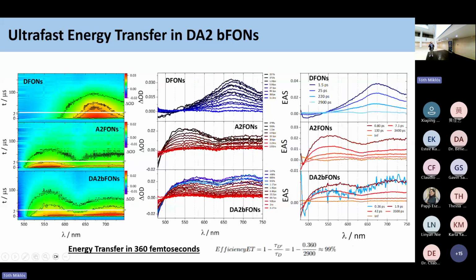Going to the donor acceptor 2 nanoparticle, we can see that the behavior is the same, but if possible, even more efficient. In fact, also in that case, it is kind of difficult to follow the evolution of the donor into the acceptor. Everything is really fast. And if we take a look at the evolution associated spectra, again, the first transient that has been assigned to the energy transfer has a sub-picosecond lifetime of about 360 femtoseconds. So this brings the overall process to an even higher efficiency if we take into consideration a similar model.